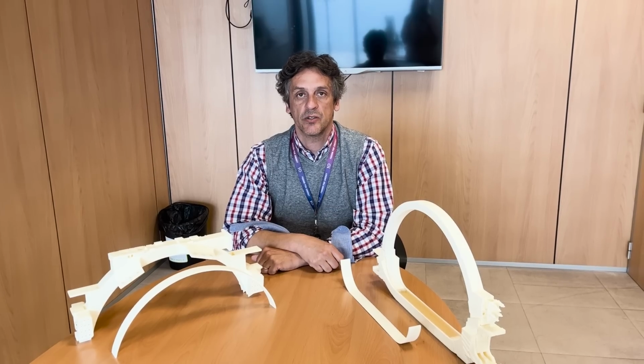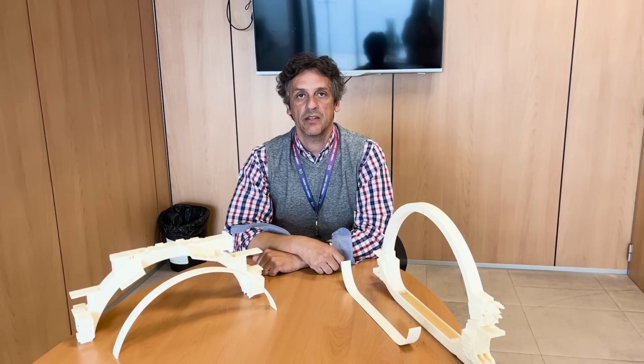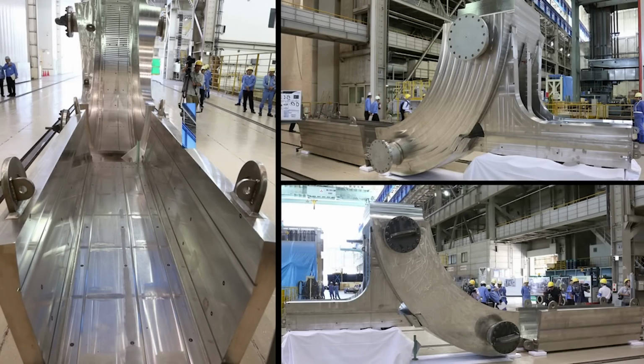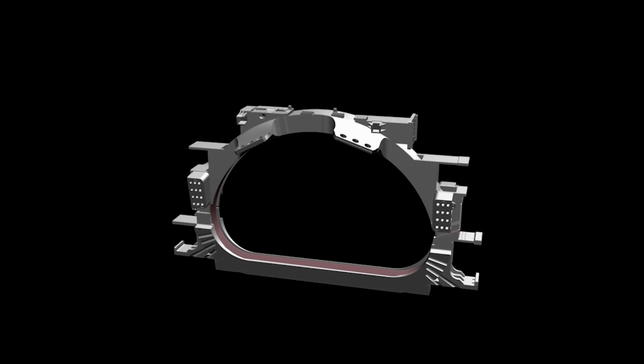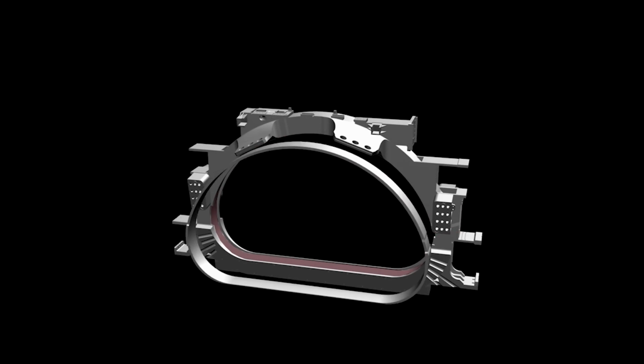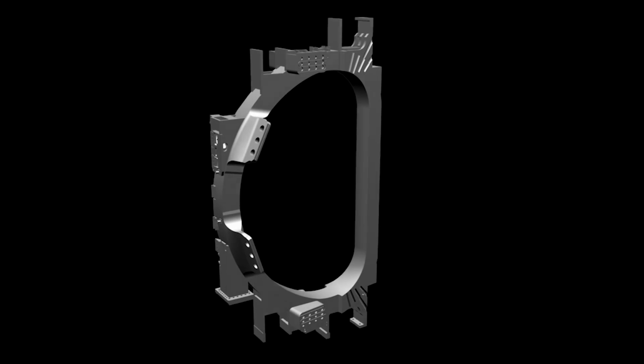The insertion in Europe is done in Italy, in Marghera, close to Venice, and in Japan, in Kobe and in Kure. The subassembly is composed of several segments. The segments are fabricated with many machining and welding operations. The fabricated segments are welded into one big 16-meter long subassembly. Because the thickness is quite large, like 20 centimeters, there is a big fight against welding deformation.